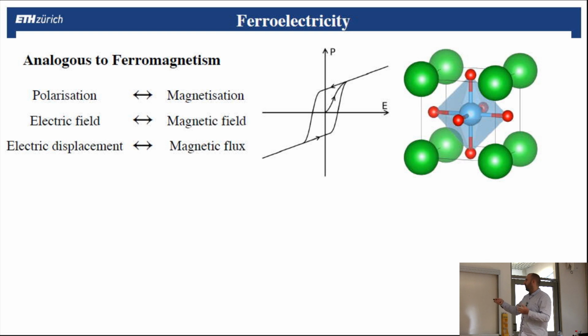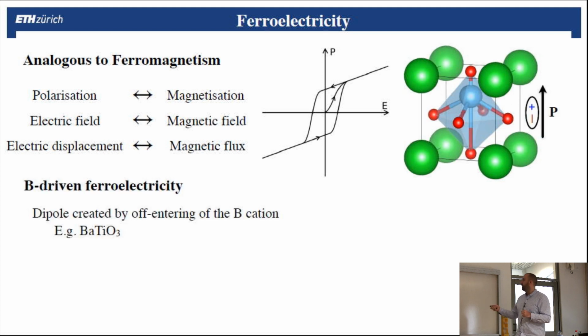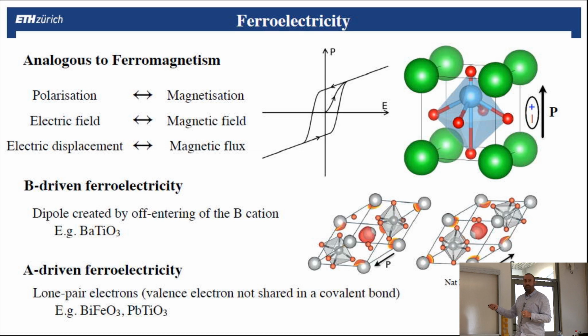Some of the ferroelectric materials also have this type of structure, and ferroelectricity can have two origins. The first origin can be by displacing this central atom out of the center of the cube, and this will create a dipole, which will induce the polarization. So that's one way to engineer or to induce ferroelectricity. Another way is not to do it in the B site, but on the A site in the corner. And this is actually done by having electrons that are not bonded. They are not participating in the bond with another atom, and they stay free around the atom. And here you can see what would be the electronic density of these electrons. And this will also create a distortion and polarization, or in the opposite direction here.